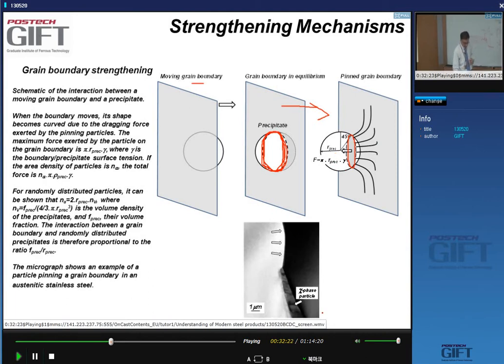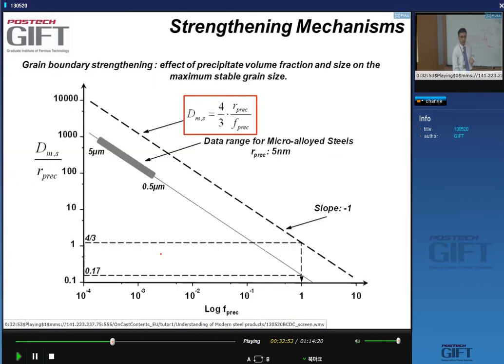For instance, here you can see you have two grains. This grain obviously bulges out into this grain. But you can see here that at this particle, the contact zone exerts a dragging force on this grain boundary that wants to move to the right. And there is a very simple law that relates the size.